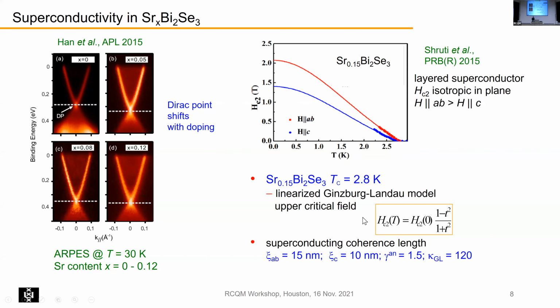And you can, of course, then fit this with some linearized Ginzburg-Landau model, and you can extract some parameters for the superconducting state. Well, we thought we can actually do this better. So we actually prepared this crystal. We can also measure in this temperature range, because this was only down to about 2.2 Kelvin.